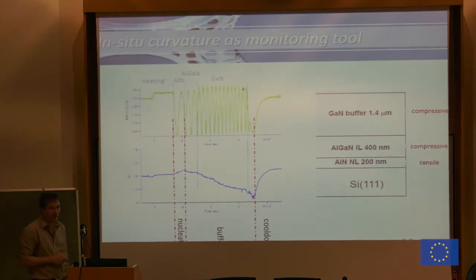The plot here is just an interferometer. So it is a red laser, and because of interference, you see how fast you are growing your material. So we see that you have different growth speeds for aluminum nitride, AlGaN, and gallium nitride. And the plot here at the bottom is an in situ bow measurement. So it shows you, relative to this 0 level, how the bow behaves as you are growing.